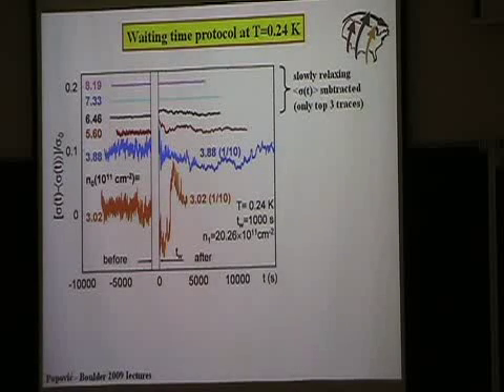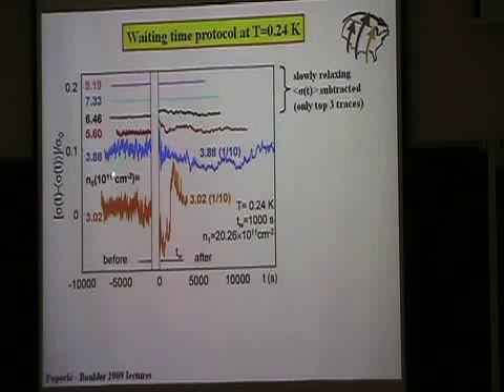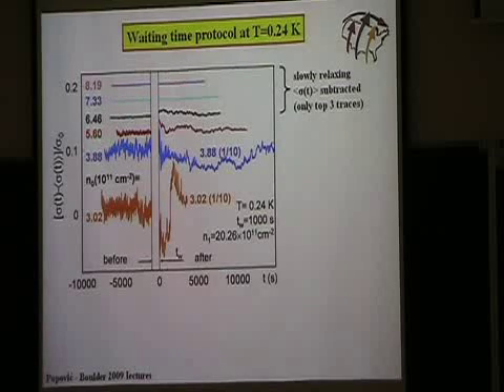Well, here is an example of the data obtained at lower temperature, and here on the left side I have the time dependence of the conductivity for several different densities. These are initial densities, so during this waiting time here in the middle we go to the same high density, relatively high, and then we come back to the original density. So you see these data on the left before this perturbation were obtained simply after cooling the sample to the measurement temperature. So you can see that there are no visible relaxations after this cooling down, but you can also notice that since these are divided by their corresponding average values, at high densities, the curves look kind of flat, but at lower densities, they become much noisier.